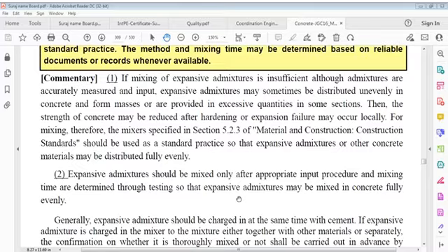I say again, if mixing of expansive admixture is insufficient, although all the admixtures are accurately measured and input, expansive admixtures may sometimes be distributed unevenly in concrete, which forms masses, or are provided in excessive quantities in some sections. Strength of concrete may be reduced after hardening, or expansion failure may occur locally. A mixer specified in materials and construction standards should be used.